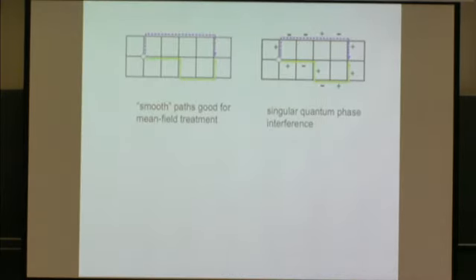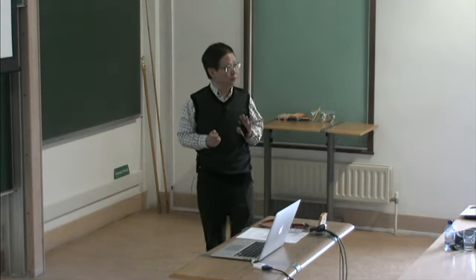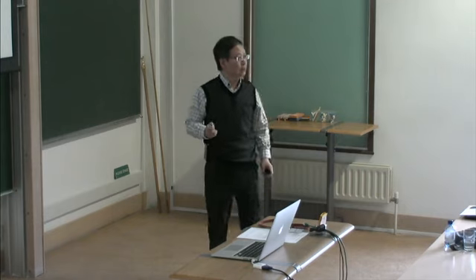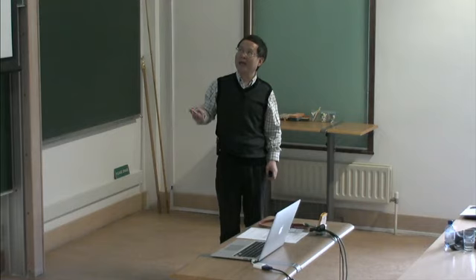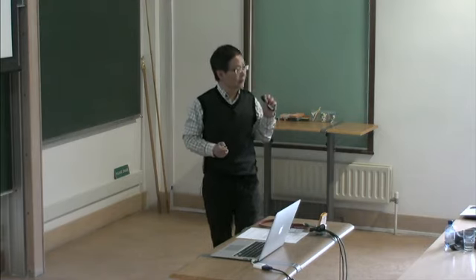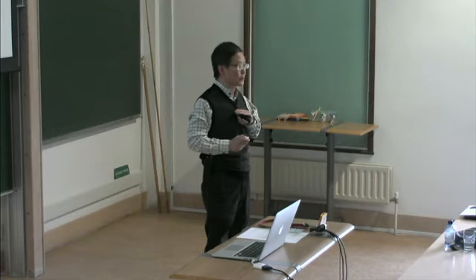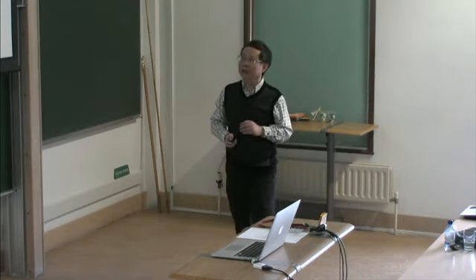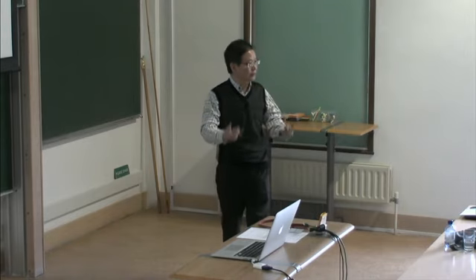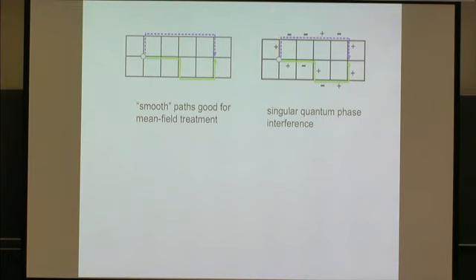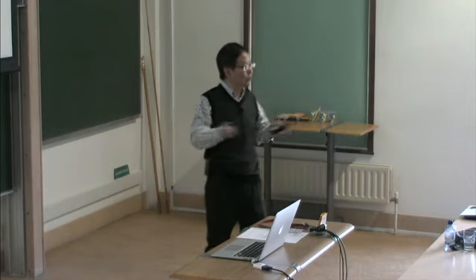What we learned here is that a charged particle moving in the background, the vacuum actually full of spins, will pick up non-trivial sign structure. And this creates a tremendous problem for our perturbative approach to this problem. Because in a conventional system, if the path is long enough compared to the lattice constant, and the path becomes very smooth, we can use a semi-classical approximation, and the mean field theory would make sense. We can create a saddle point state and do perturbation. But this sign is very singular, because one sign change will totally change the nature of each given path. And so you cannot do any approximation.